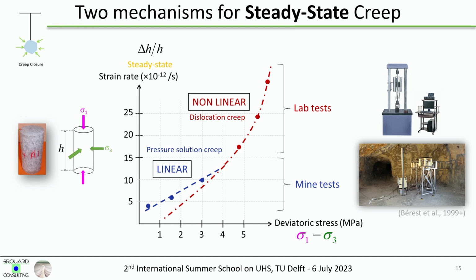And when you would like to compute the behavior of a salt cavern, you need to take into account a much larger volume of salt around the cavern, where the deviatoric stress is much less than 5 MPa. So that's why, for a long time, it started here in the Netherlands with Jan Urai and Chris Spiers. They found that when we look at the micro scales, the behavior of salt at very low deviatoric stress should be linear. This is an idea that they published in Science in '86. It was just an idea, but nobody really understood or believed this at that time. And at the end of the 90s, with Pierre Berest, we started to perform testing in a mine at this low deviatoric stress. It was a way to check this assumption made by Janos and Chris.